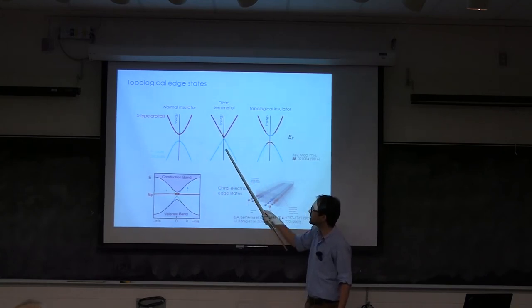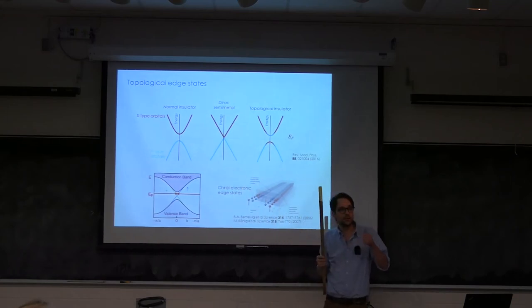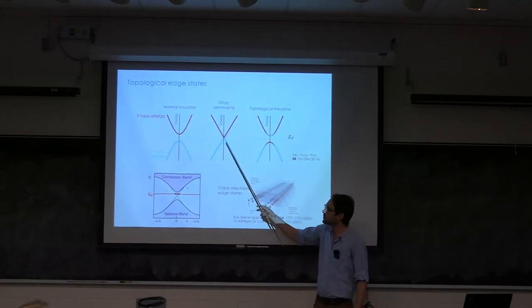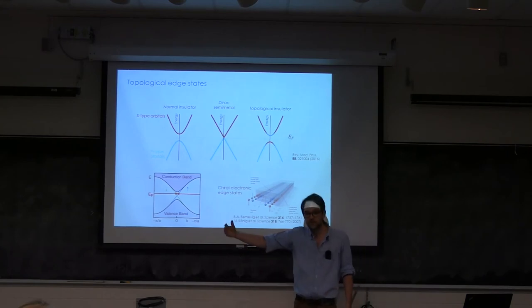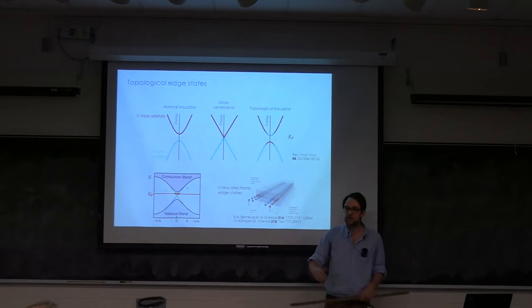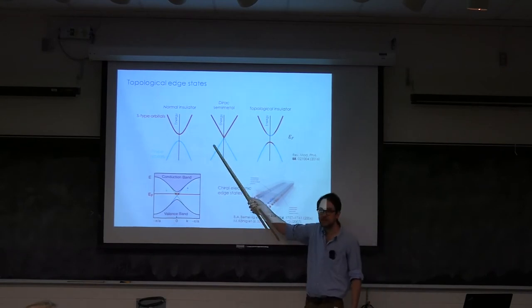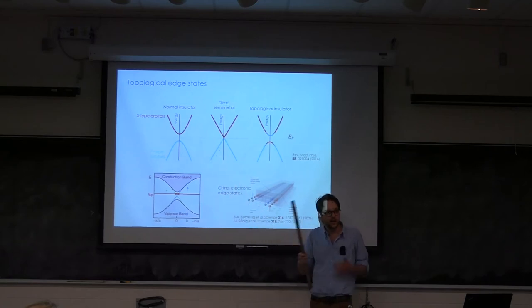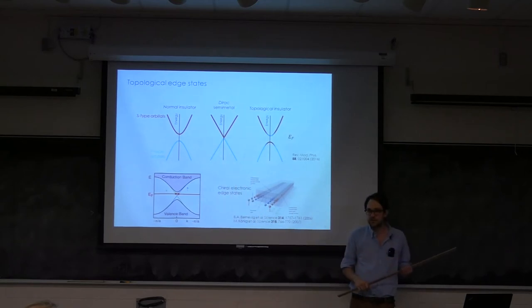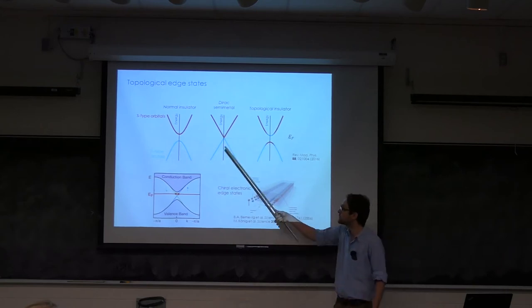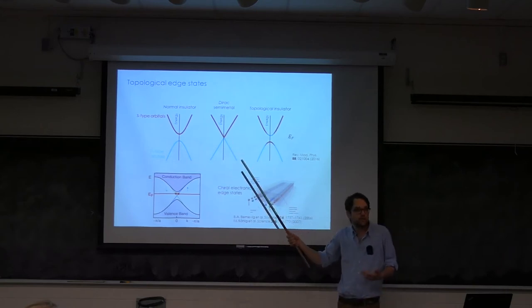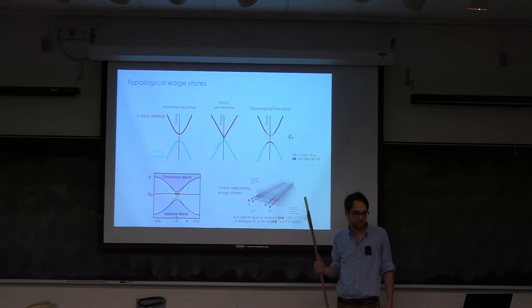In both cases, you have one direction that is sigma plus polarized, so electrons spin up. The other one is electrons spin down. So the electrons moving across this interface, along this interface, cannot backscatter because that will require a magnetic impurity, reversing the spin. And so we talk about these edge states as protected, topologically protected edge states. And usually this is what we want to harness in these materials. The robustness of these states, we want to study how we can make different families of these states and how we can take profit of their robustness properties.